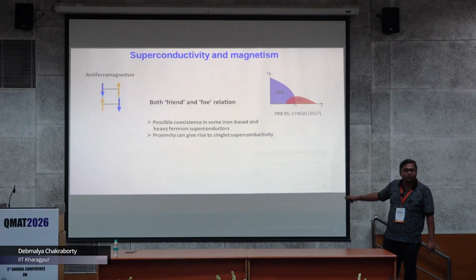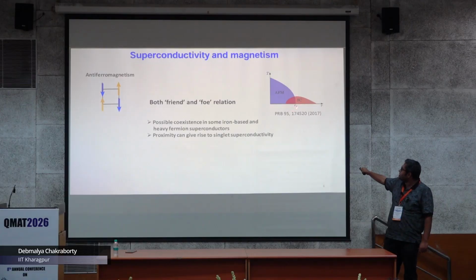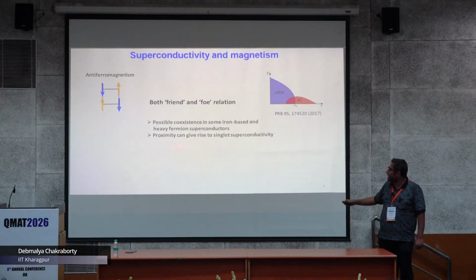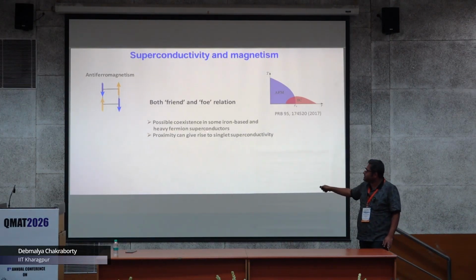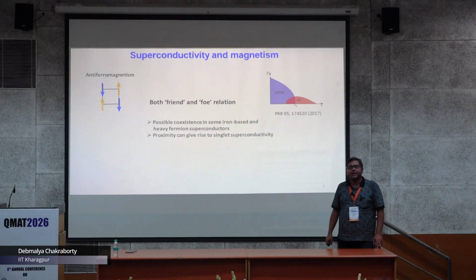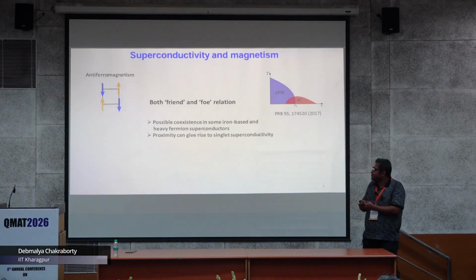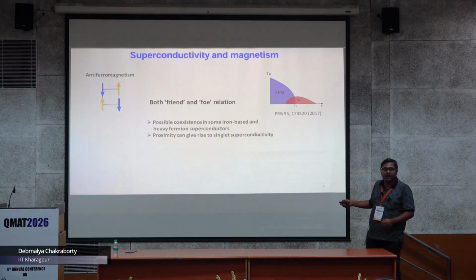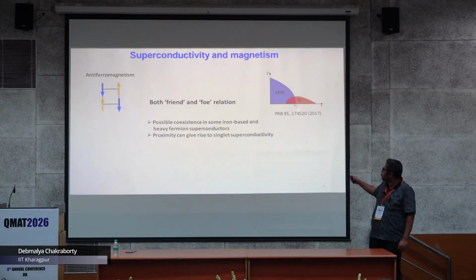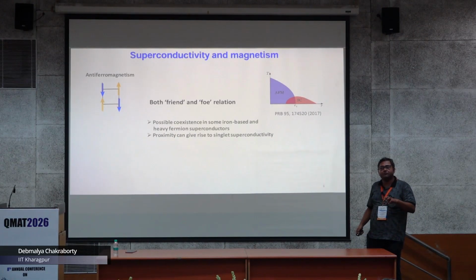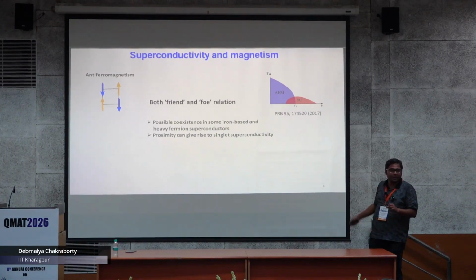If you look at antiferromagnetism, there are very small coexistence places. In some iron based and heavy fermion superconductors you can get coexistence. You can also have a phenomenon that near a quantum critical point of an antiferromagnet you can get a superconducting dome. That means due to the fluctuations of the antiferromagnetic quantum critical point you can get superconductivity.